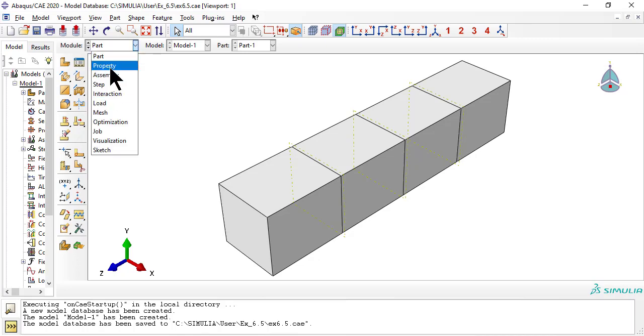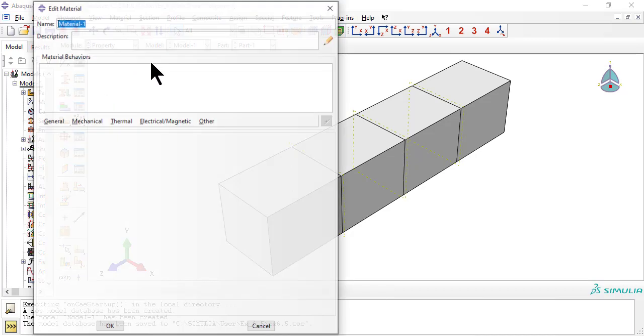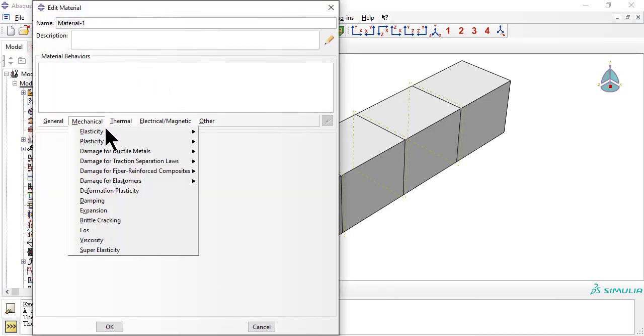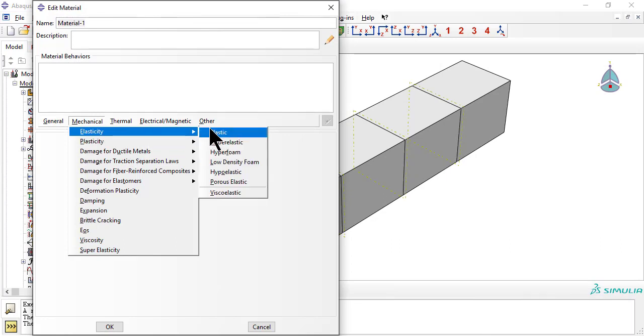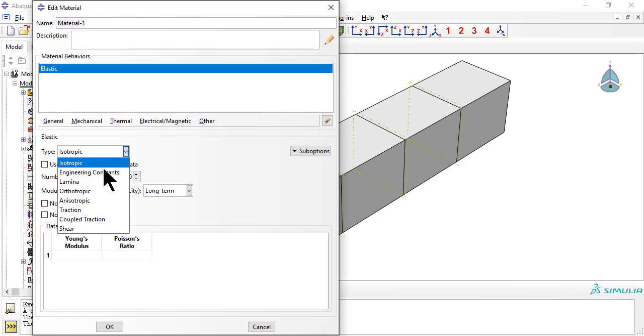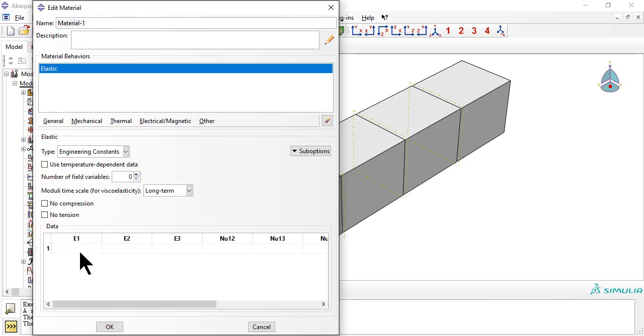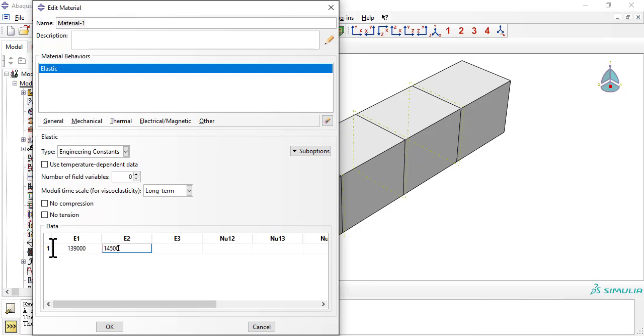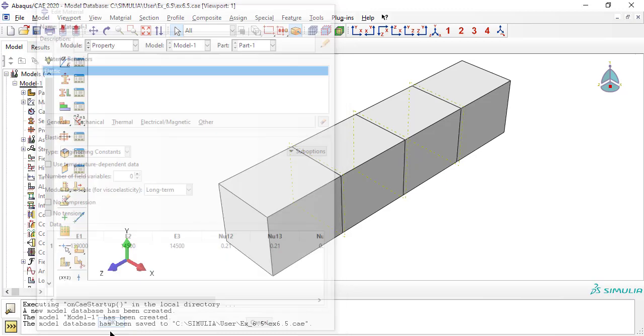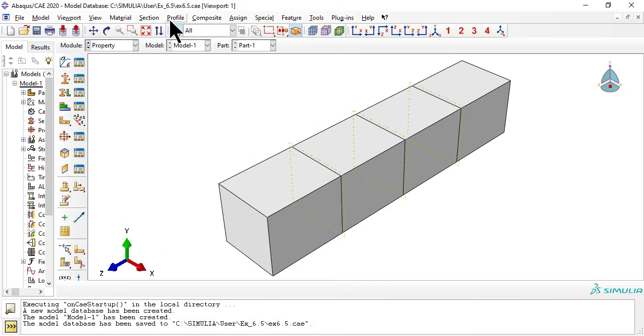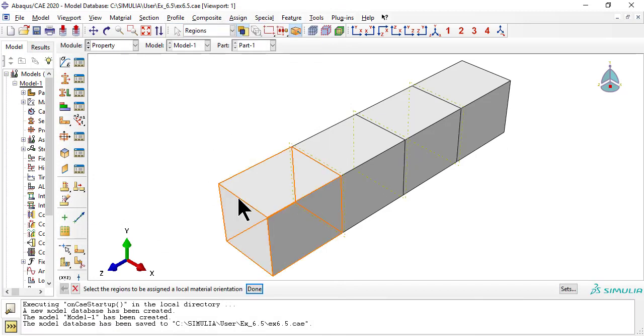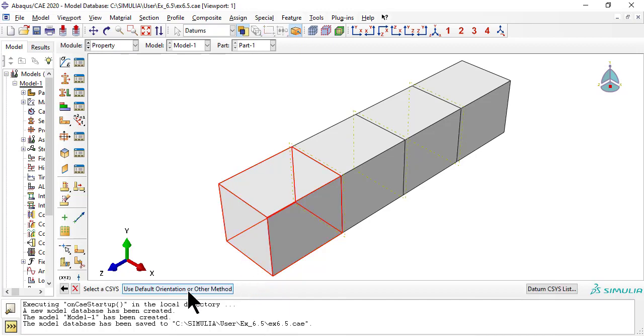For 3D modeling, the properties of each lamina are those of an orthotropic material with nine properties, but a fiber-reinforced lamina has only five properties, so some are repeated.